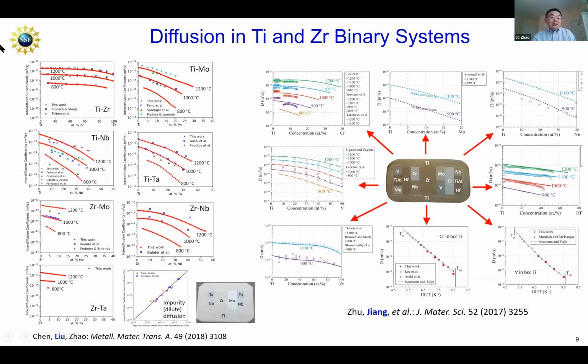And for us, this data, as you extrapolate in this one, agrees with the independently measured impurity data really well, right? For some of the data sets, if you extrapolate that data to the impurity, there will be disagreement with the literature one. So we have very good confidence, because those are literature impurity data and this is our data. We did not input the tracer impurity data in our modeling process. So this is an independent check of how reliable the data sets are. Okay.